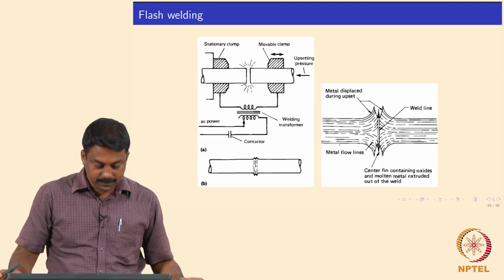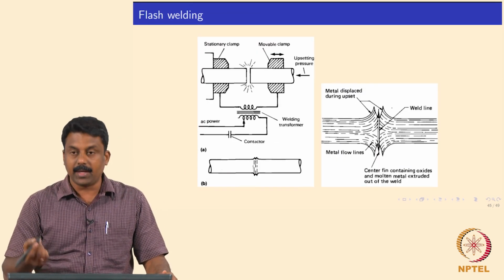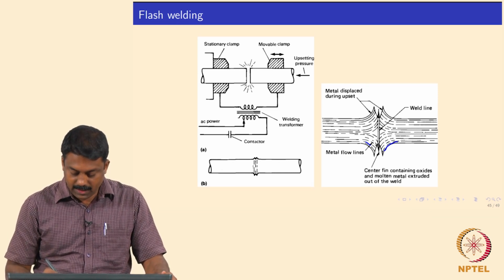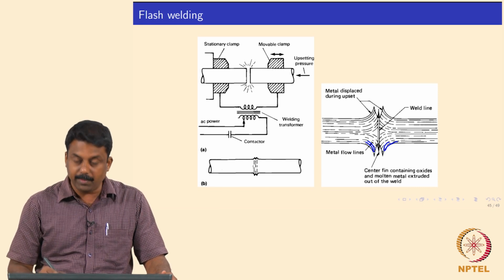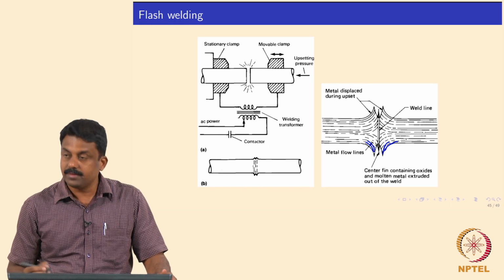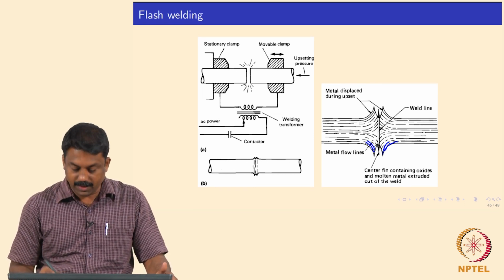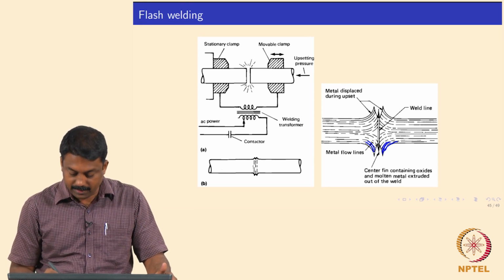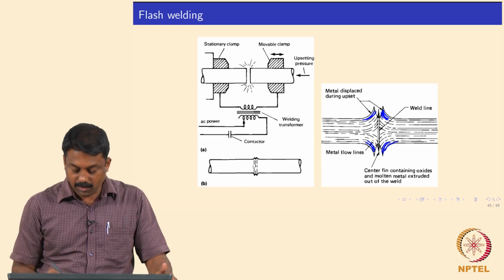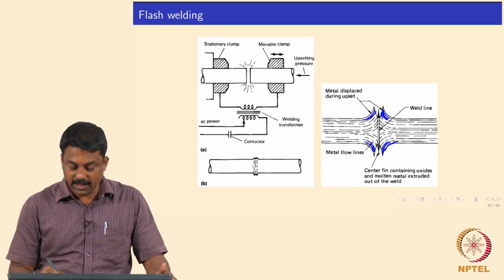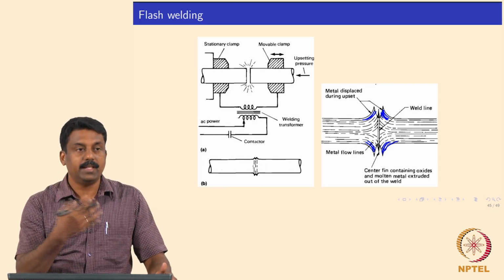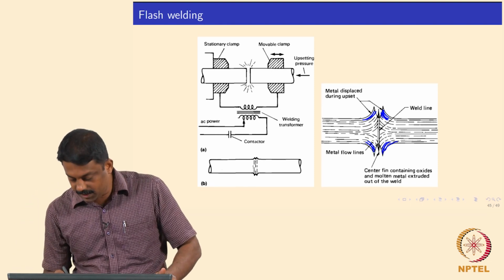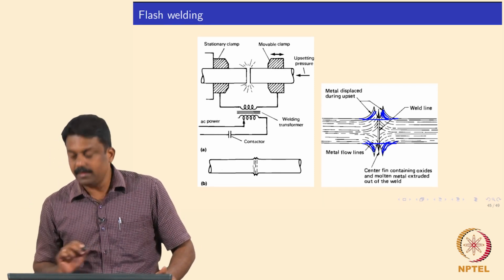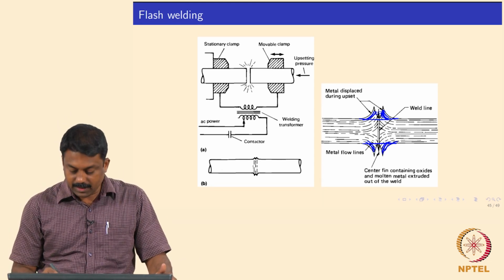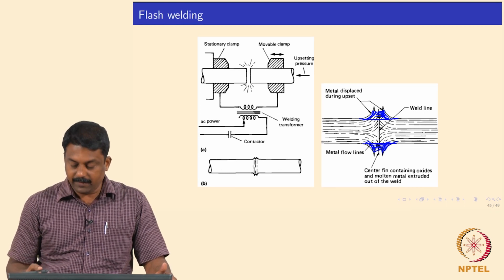In both the processes, the flow of material upon upsetting takes place in such a way that you will have a mechanical deformation, and in most cases the interface contaminants are pushed to the flash region. So the material is deformed and displaced toward the flash regions. In flash butt welding it is done very effectively, because whatever goes out is liquid. The liquid would carry all the inclusions and contaminants which were there even before welding, and subsequently if you machine this off, you make a very nice joint, and you take the interface contaminants out, you will end up having a nice weld.